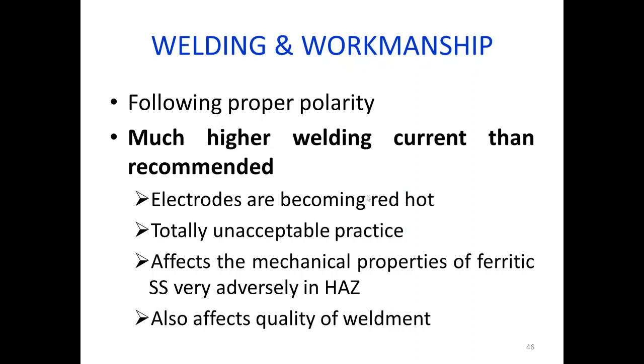If you go on keeping more current, the electrodes become red hot, which is a totally unacceptable practice. It affects the mechanical properties of ferritic stainless steel very adversely in the heat affected zone, not the welding area, which will be heated more. So the properties of the metal will be deteriorated. It also affects the quality of the weldment. These are all we have to keep in mind.